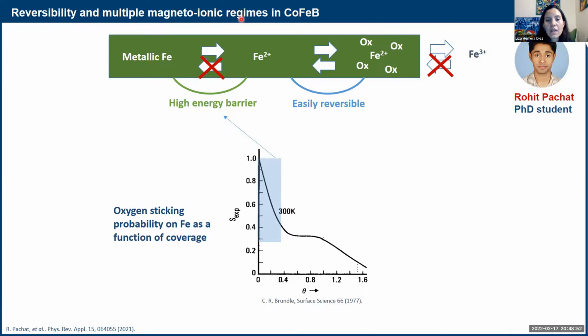And so then what happens next? Now you have iron oxide, and you keep adding oxygen. Iron has another oxidation number, which is 3+. But to go from 2+ to 3+, you could also go through mixed oxides, 2+, 3+. But before you even do that, you have to add even more oxygen around the iron 2+ to actually create a chemical environment that would, in the end, create this charge transfer and then really oxidize the iron even more.